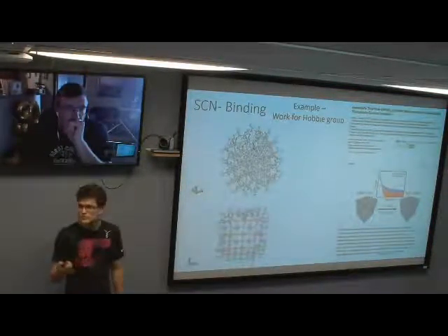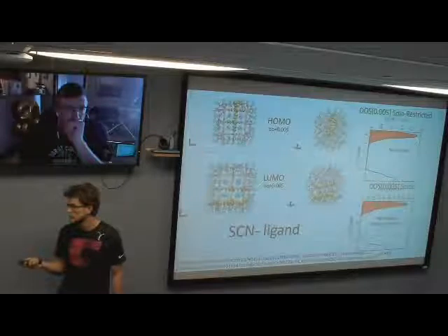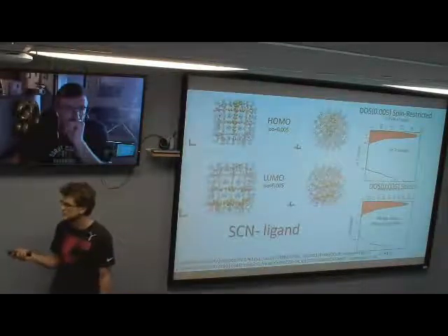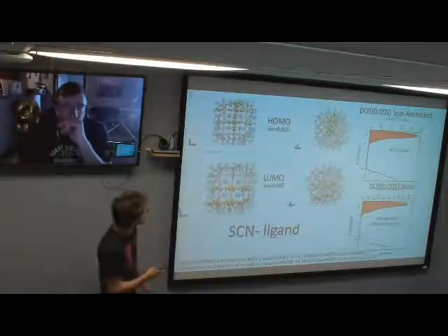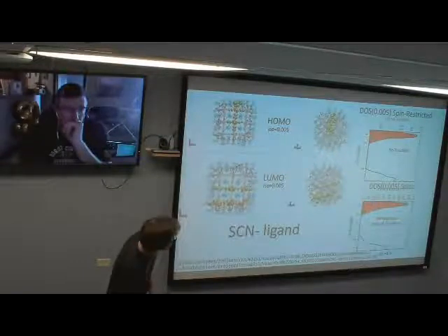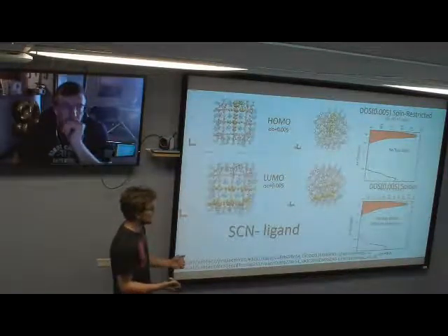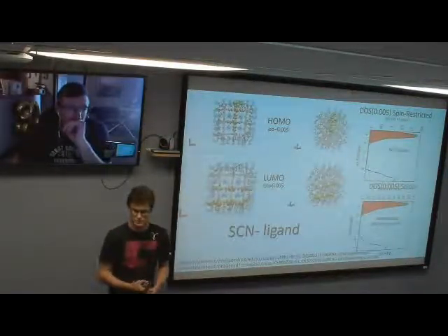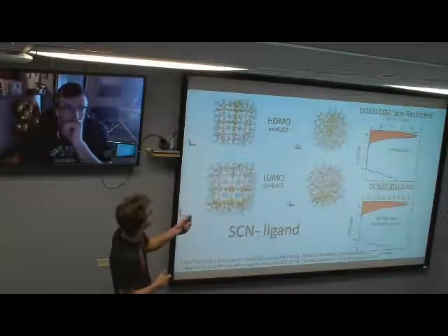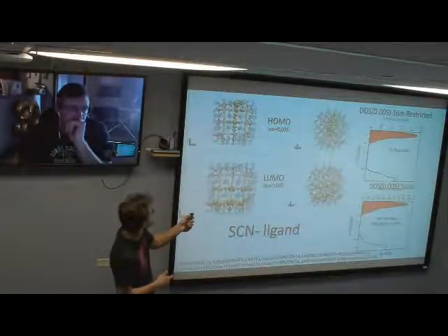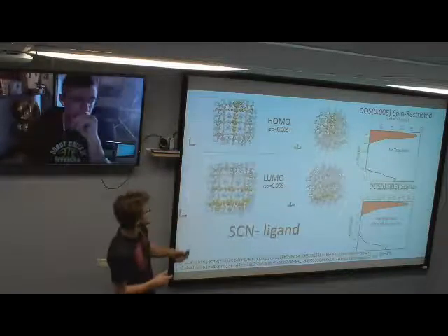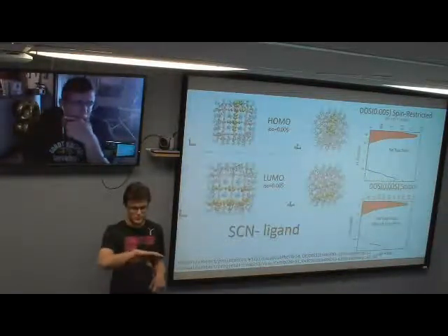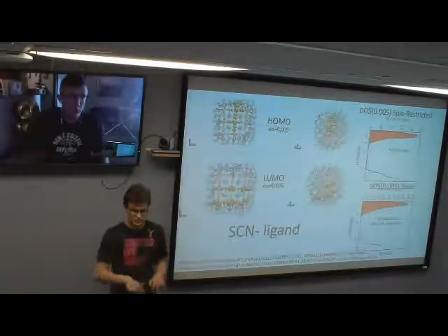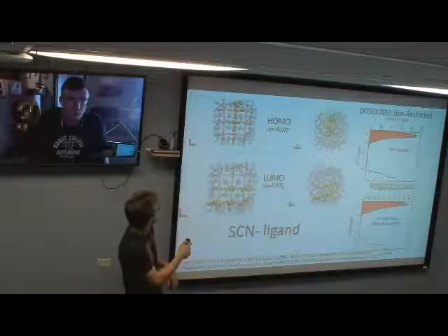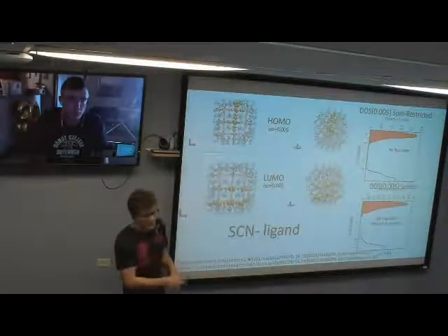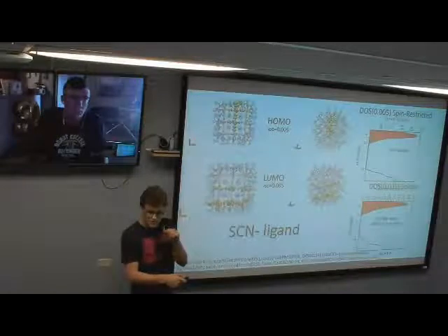So just some preliminary orbitals from these. From the density of states, you don't see any obvious trap states. Again, I would have to look at PDOS to see what exactly they are, but at the HOMO you can see an interesting feature. It seems like the ligand actually hybridizes with it, and then the orbitals stick out with the ligand. So it's kind of like a conductive type. And again, you took out the ligand, or replaced it, ligand exchange?